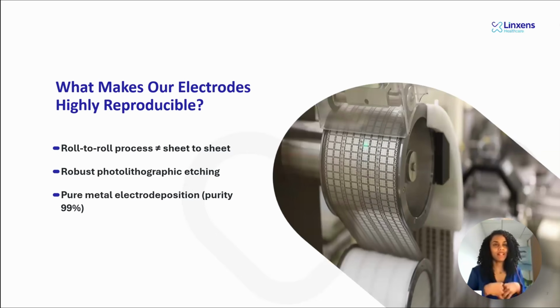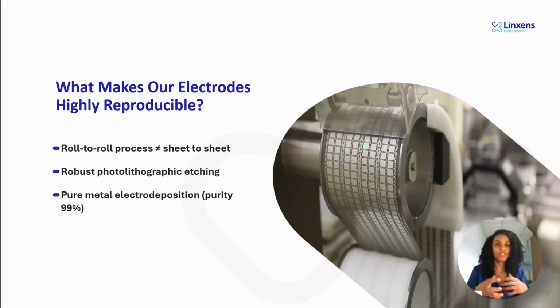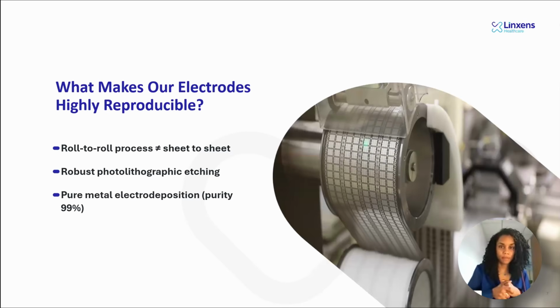because it is a pure metal deposition. So if you compare with screen printing, in a metal ink, you have a resin, you have some solvent, and all these components will impact the final conductivity of your electrodes, of your transducer. So thanks to our electrodeposition, you will have a pure metal deposition. So the conductivity of your electrode at the end will be better in comparison to a screen printing system.